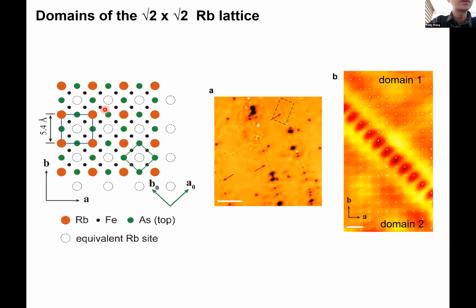These are some details of the lattice. In this model, if the rubidium has a root 2 by root 2 reconstruction, there are two equivalent occupation sites of the rubidium atoms, the orange one and the dashed circle. So there should be two different domains, and we indeed observe them. In this image, we can observe the domain walls, and the upper domain and lower domain have a half unit cell offset, as shown here.